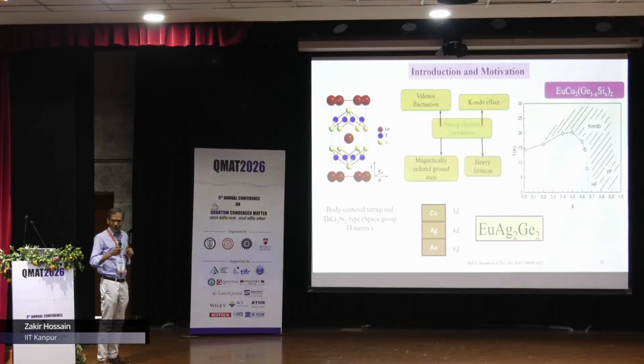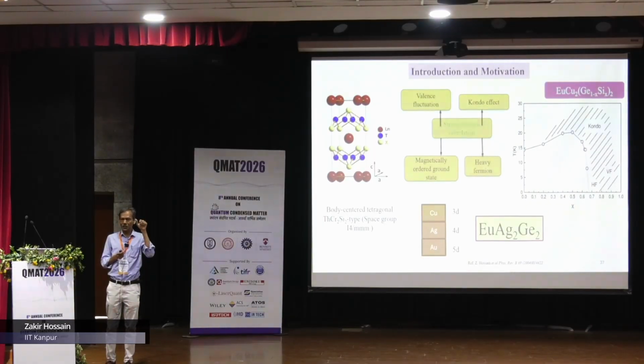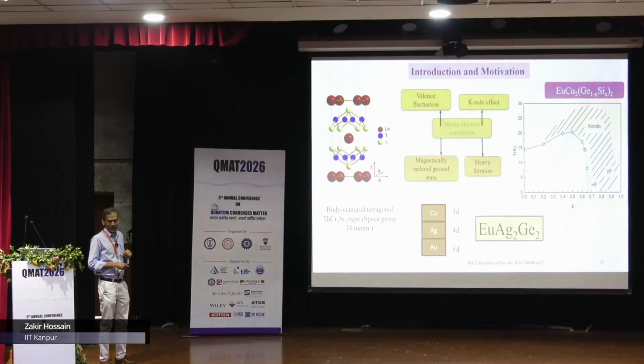I have just the last 2-3 minutes. I will quickly go through the last compound, europium silver two germanium two. Europium compounds are similar to gadolinium; they are also spin-only systems, with 7 electrons, S equal to 7/2. The interest is that, like cerium, for which there are many heavy fermion compounds and superconductors, europium can also fluctuate between 7 electron and 6 electron configurations. The 7 electron one has J equal to S equal to 7/2, and the 6 electron version has J equal to 0, with L equal to 3 and S also 3, where L minus S gives cancellation. So it becomes non-magnetic. So it can fluctuate between magnetic and non-magnetic, which is also true for cerium compounds. If cerium compounds can show a lot of interesting effects, why not europium?